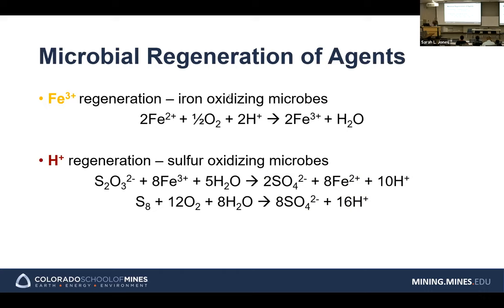So how do we regenerate? How do microorganisms regenerate those agents? As I said, Fe3 plus regeneration, ferric ion regeneration, uses iron oxidizing microorganisms. So in the previous slide, pyrite will be oxidized by the ferric ion, and the ferric ion becomes ferrous, Fe2 plus. And Fe2 plus is going to react with oxygen in an acidic solution, and it's going to form a ferric ion. So this reaction happens naturally, but the kinetics is very, very slow. So without any microbial activity, it happens, but not fast enough to provide this ferric ion. So that's why we use specific microorganisms that oxidize the ferrous ion to a ferric ion.